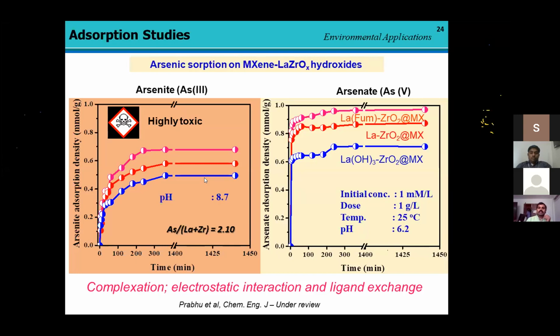capacity for the arsenate phase, due to the pH of the solution, where for arsenate the pH is 6.2, in which arsenic is in the +5 oxidation state, whereas the oxidation state of arsenite is 3 at pH 8.7. Until now, arsenite has been considered more highly toxic than the arsenate species. Then we found that the arsenic to metal ratio was 2, and we confirmed that each metal can adsorb